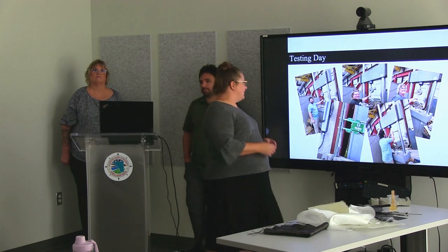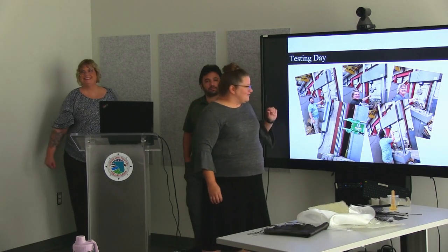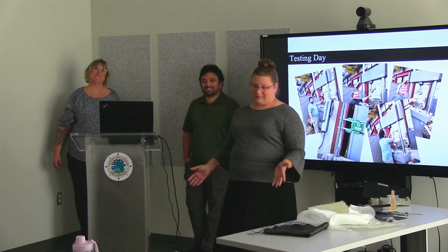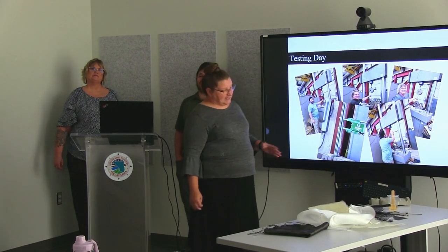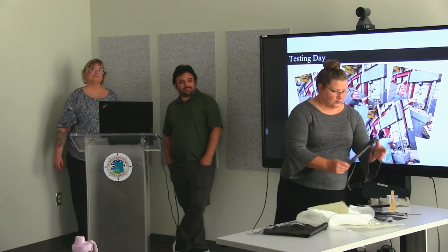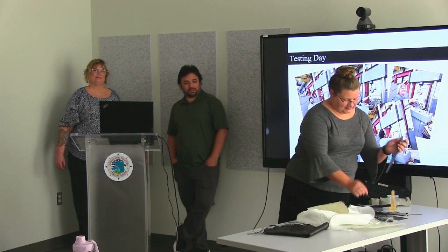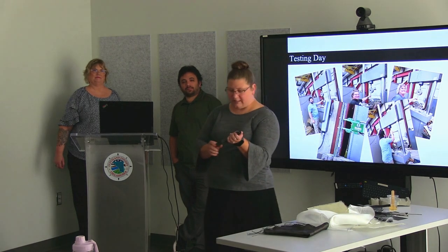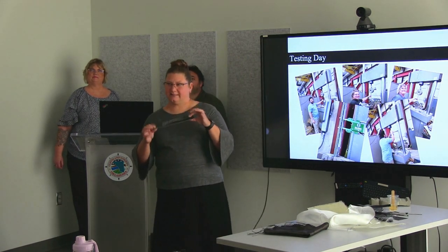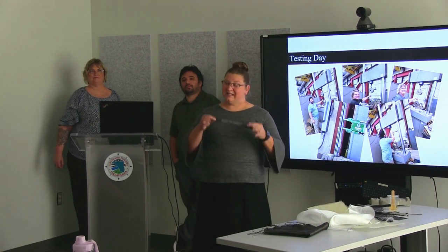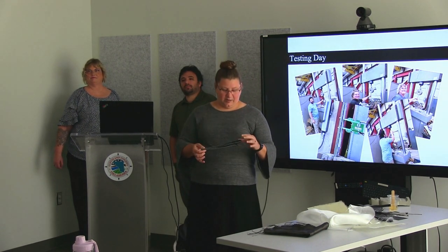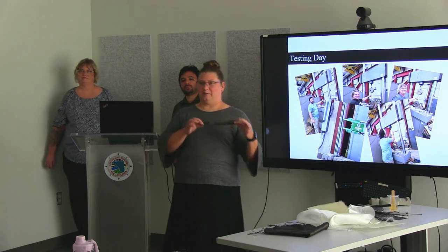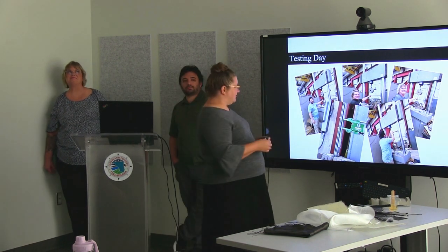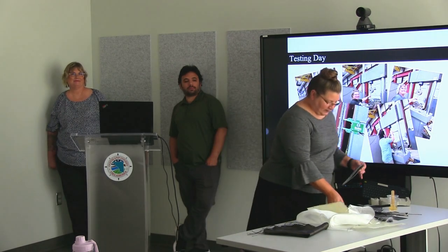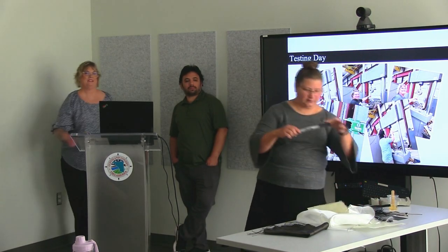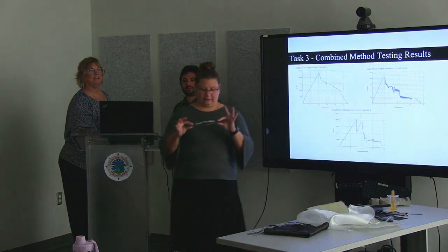So we came to testing day. This is the machine that we used. We had 3 samples to test. Our first test, the way we had it clamped in the machine, it was a little bit too far on the ends because our sample's so thick. It didn't have a good grip, and our bonding of our tabs kind of failed before anything else. So for the second test, we adjusted and put our grips down a little bit further.